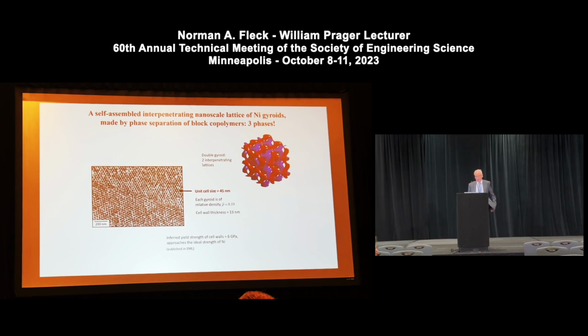In the nanoscale world, self-assembly is a useful way of making nanoscale lattices. The nickel gyroid, for example, is a good example. One can make, by phase separation of block copolymers, two interpenetrating phases of gyroid lattice. And this is actually a 3-phase structure because some porosity is left. This really is a nanoscale lattice because the cell size is down at 45 nanometers. The wall thickness is, say, 13 nanometers. And one can replace the polymer by various other materials such as nickel.